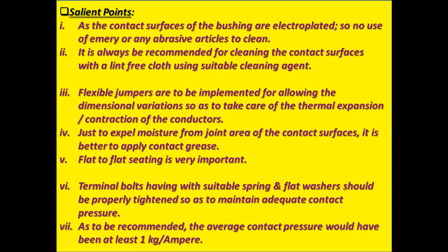Flexible jumpers are to be implemented to allow for dimensional variations, so as to take care of the thermal expansion or contraction of the conductors. Just to expel moisture from the joint area of the contact surfaces, it is better to apply contact grease. Flat to flat seating is very important. Number 6, terminal bolts with suitable spring and flat washers should be properly tightened so as to maintain adequate contact pressure. As recommended, average contact pressure should be at least 1 kg per ampere. That is 1 kg per ampere current.